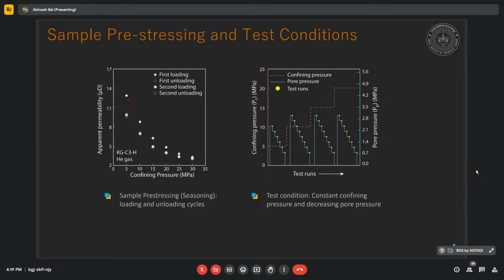To eradicate this, we do a second cycle of loading and unloading, and we found that after 2 cycles, the apparent permeability at each stress condition is mostly overlapping. Therefore, whenever you are using any compressible rock type, pre-stressing is very important to accommodate the stress, so that you can exactly simulate the reservoir condition. Then you start your experimental condition, applying your test condition and measuring the apparent permeability.